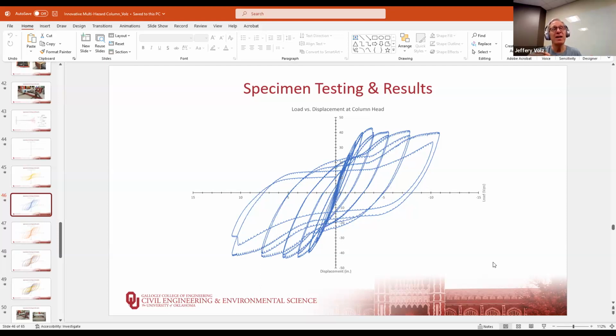And if you think of an interaction diagram for reinforced concrete, you know how it's kind of got a, I don't know what that shape is. Not quite a bell shape, but at low axial loads, as you increase the axial load, you actually increase the flexural resistance until you hit the balance condition, and then additional axial load will decrease the flexural resistance. So typically, most of our bridge piers are in this lower range. So in this case, if we put more axial load on the column, we'd actually increase the flexural capacity. So we wanted to have a relatively low axial load. And this is very consistent with previous research, where they target that amount.